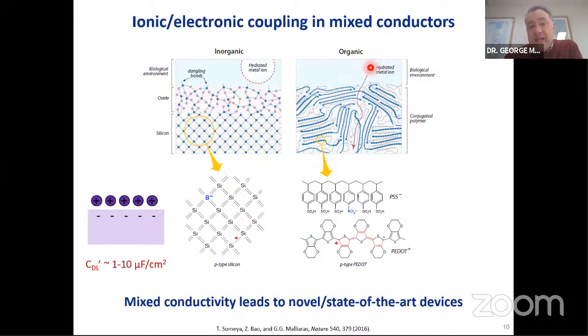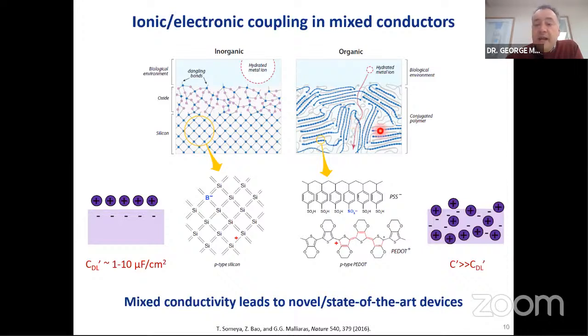However, there are materials that allow transport of ions in the volume of their bulk. This is an example of a conducting polymer called PEDOT:PSS. It consists of two polymer chains. It is a degenerately doped P-type semiconductor that is able to uptake ions in its volume. So it's a mixed electronic ionic conductor. And in this case, you can have coupling of electronic and ionic carriers in the whole volume of the film. And that gives you a capacitance per unit area that largely exceeds the double layer limit and allows you to make novel, state-of-the-art performing devices.